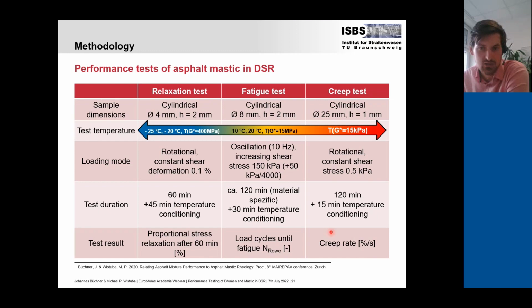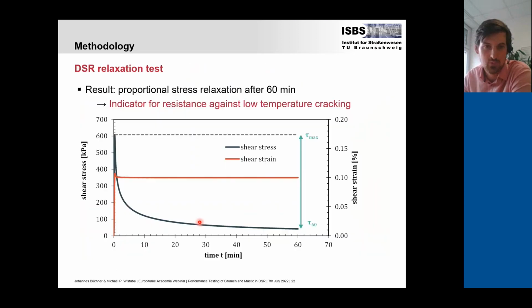The test duration is already included here. You can see we tried to reduce the testing time as much as possible. So testing time 60 minutes, 120 minutes, 120 minutes. Actually, now we reduced this already with further development. So the whole test system can be applied within 1 day to determine the performance behavior of an asphalt mastic. I will start with the relaxation test at low temperatures.